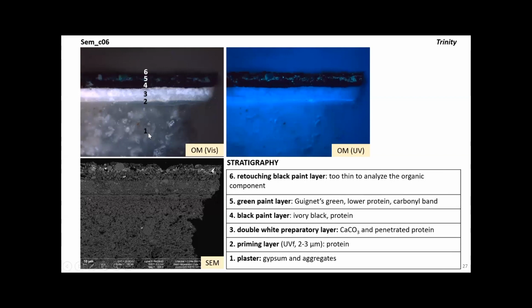And thanks to the cross-section, it is possible to see the stratigraphy of the sample, composed in this case by 6 layers. An important information coming from this analysis is, for example, related to the presence of this intermediate primer layer. In this UV fluorescence image, it is possible also to see a thin fluorescent layer. And this information is obtainable only by the analysis of the cross-section. In the same image it is possible to observe the different morphology of the materials.